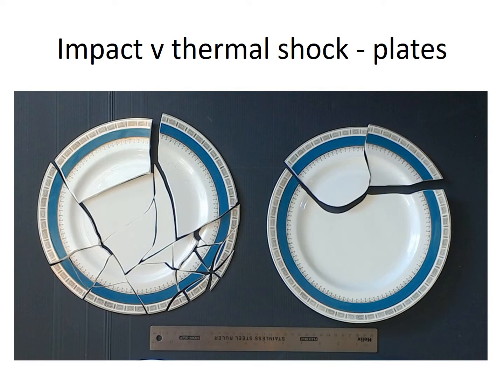So here we can see the difference between impact and thermal shock on two identical plates. The one on the left was broken by dropping it from a height of 1 meter onto a hard surface, striking the ground on the base. The plate on the right was subject to uneven heating over a gas flame.